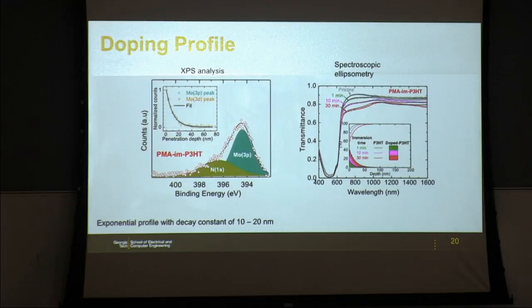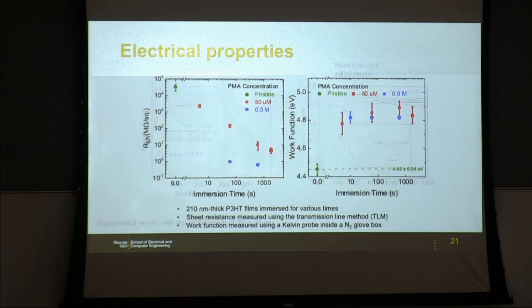So on the right-hand side, you see some spectroscopic ellipsometry data. Again, just verifying independently that we have these exponential profiles with a certain penetration depth of 10 to 20 nanometers. This is really important because if the dopant goes everywhere, your semiconducting film becomes a conductor and you don't have diodes anymore. So that's really key to be able to apply this to devices.